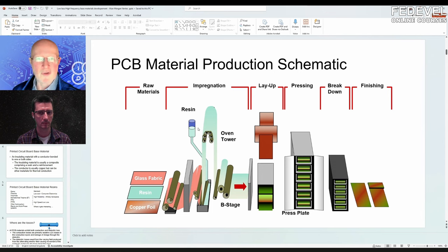They're used for improving the loss coverage that we just talked about. They're also pretty dimensionally stable. So some of the fillers don't expand and contract very much compared to resin. So if you can replace some resin with some fillers, you can reduce the overall expansion of the material, making it more reliable. You can also use fillers that help with flame retardancy. So when we've moved away from, or let's say added on another kind of flame retardancy from typically halogens that have been widely used for many, many years, you often have to add fillers which form part of the flame retardant system as well. So there's many reasons why you do that.